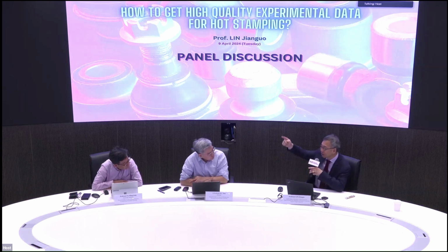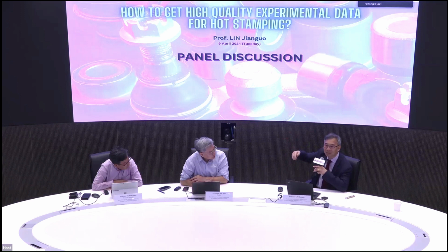That's the reason we try to reduce temperature very quickly, because we try to form the material within the austenite state. If we drop the temperature slowly, it will enter the bainite and pearlite regions. Then when we do the forming, the material is already bainite, and the ductility of the material decreases significantly. We try to form the material before the nose of the C curve. If you know the CCT diagrams, that's why they put boron in steel. Boron moves the CCT curves to the right a bit, so the required cooling rate is lower. Currently, the minimum cooling rate is 24 degrees per second.